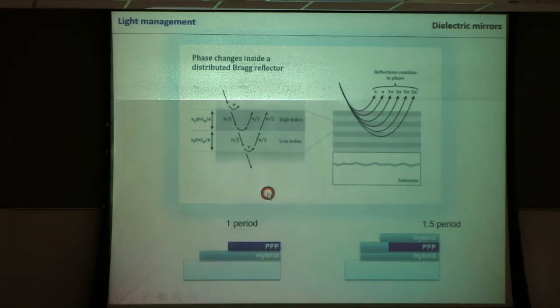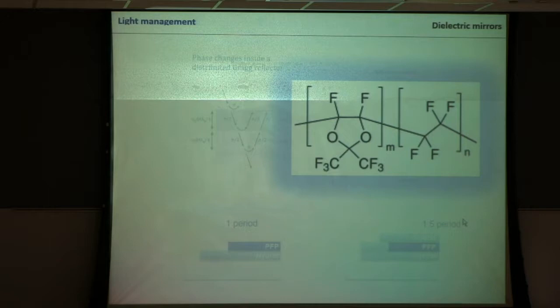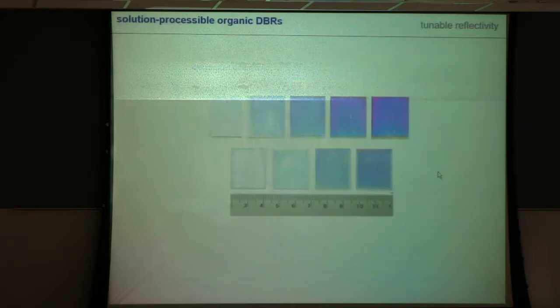And then we just stack them, and just for consistency, sometimes I show mirrors when we talk about 5 periods. So it's just a hybrid, PFP, and then 5 times. Sometimes we add in an extra layer for additional optical effects. So in that case, we call it a 1.5 period. Initially, we worked with this fluoropolymer that is commercially available. Again, why? It has the lowest refractive index, 1.29, and is pretty transparent.